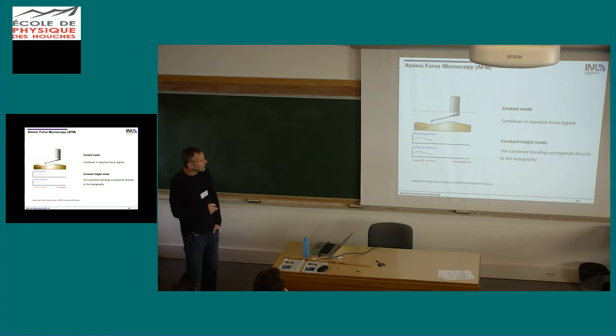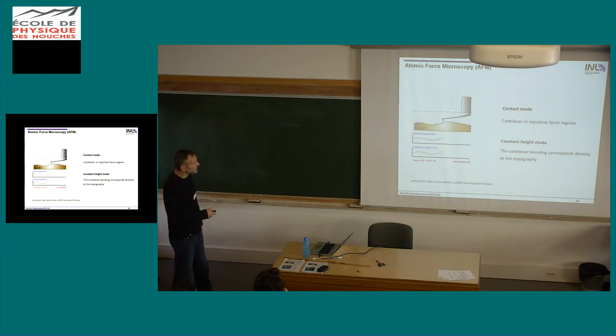Again, there are two different ways to do this. One would be in constant height mode. So this is similar to what we saw before with the scanning tunneling microscope. We just keep the Z piezo constant and just look at the deflection of the tip. So whatever the laser beam reflecting off here is doing is monitored, and this is of course proportional to the surface morphology.